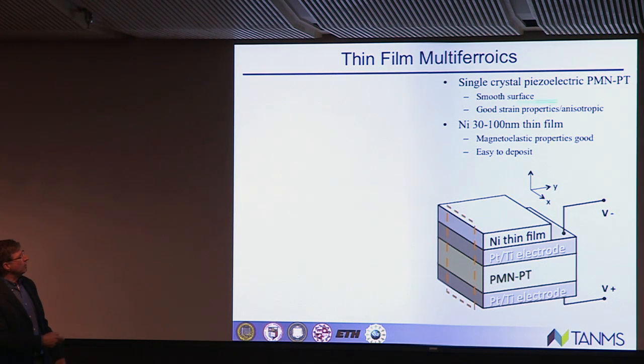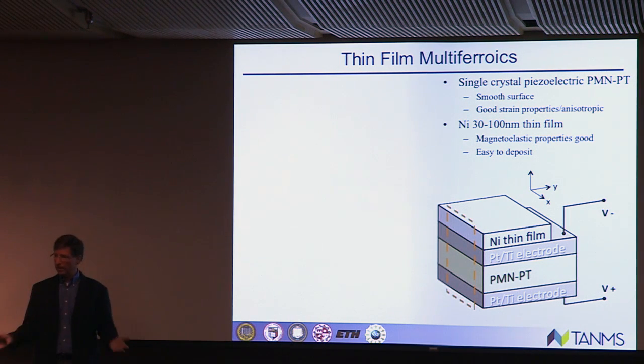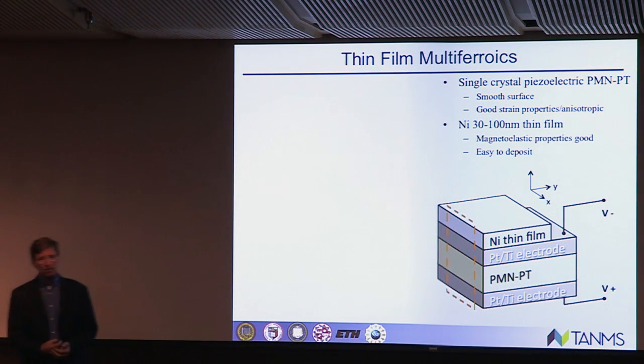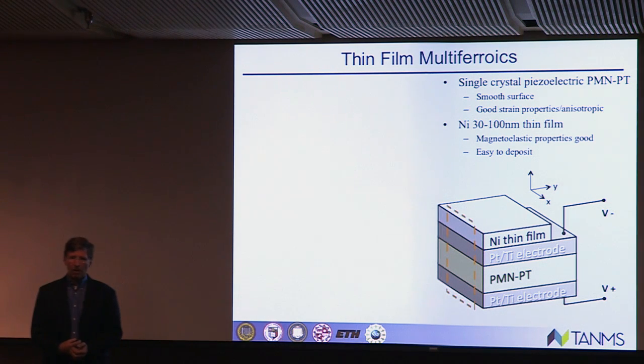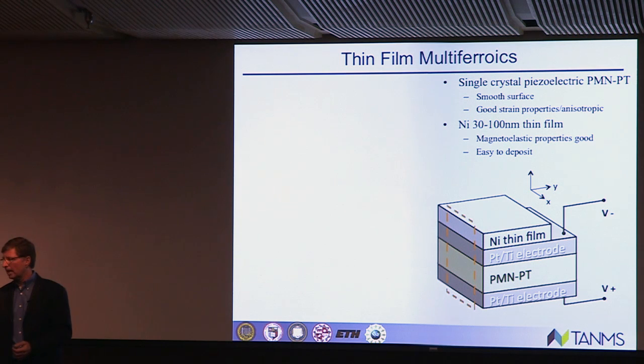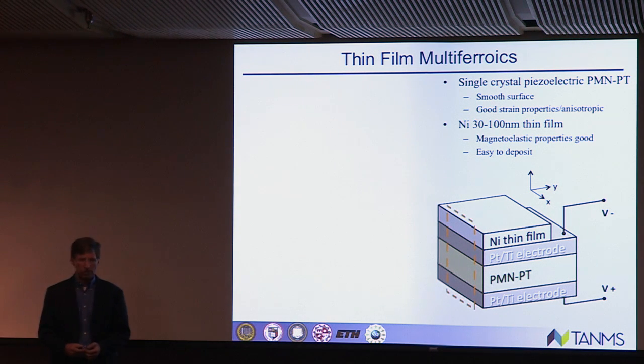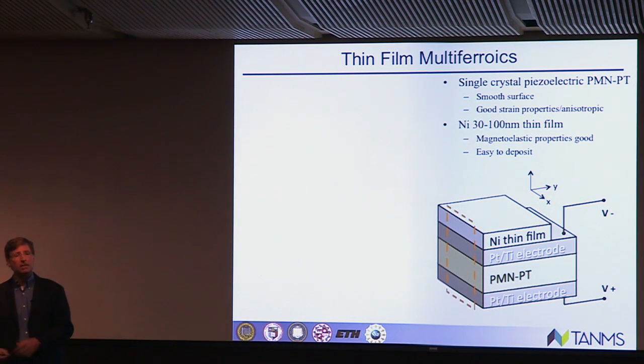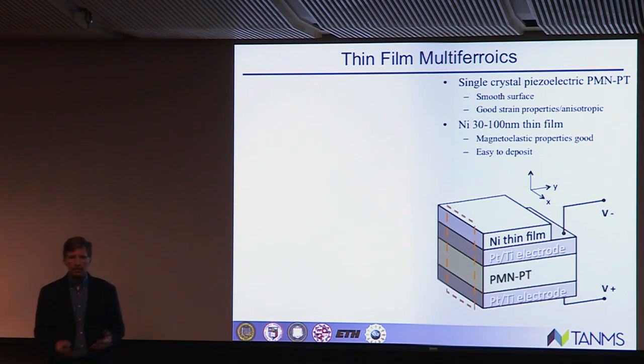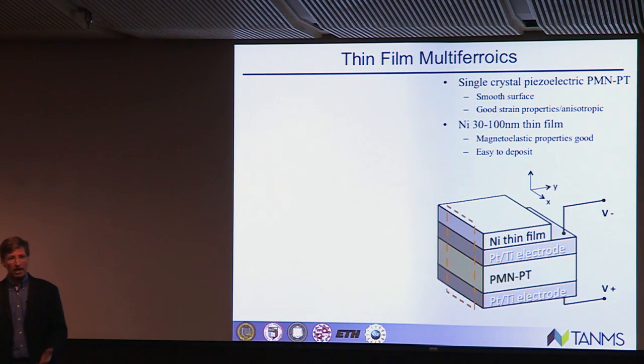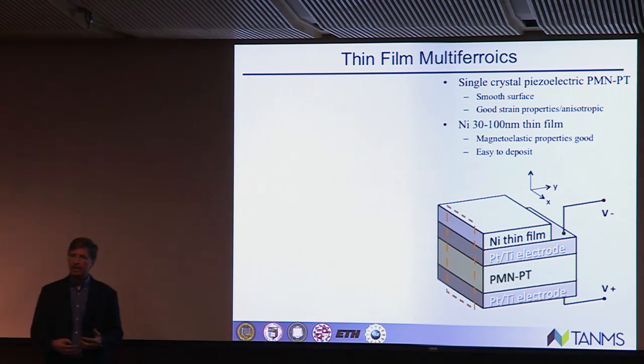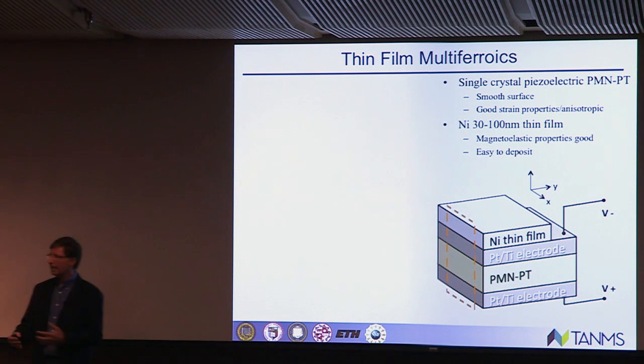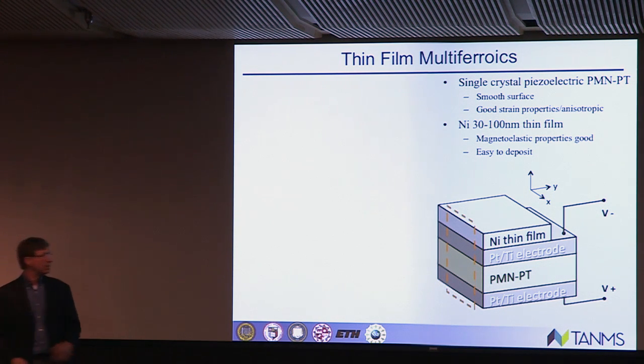Now, on the top surface, we use nickel film. Is nickel the best magnetoelastic material? No. However, it's a sufficient magnetoelastic material. It was one of the first magnetoelastic materials ever to be used in sonar transducers. So it's good, it's not the best. So you may ask, well, why did we choose it? It was easy for us to fabricate without having to go through the headaches of making very exotic materials. Because once again, we want to get close to applications and actually just identify potential possibilities.